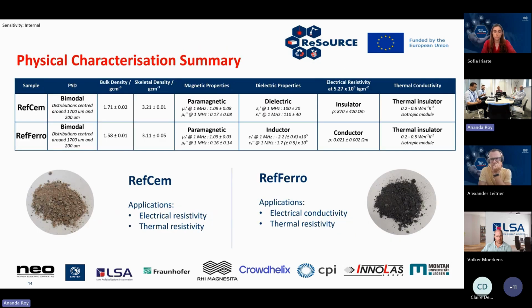We also had a look at the physical characteristics of these materials, whether or not they have interesting magnetic, dielectric, electrical, and thermal conductivity properties. What we see is that the interesting properties are perhaps that the RefCem material behaves as a dielectric and an electrical insulator, whilst the RefFerro material behaves as an inductor and an electrical conductor. The reason for that is that there's a higher amount of graphite present in the RefFerro material, so we can form conductive pathways to create that electrical conductivity in the material. Both materials are also thermal insulators, which is what we'd expect given the applications that these materials have been used in.